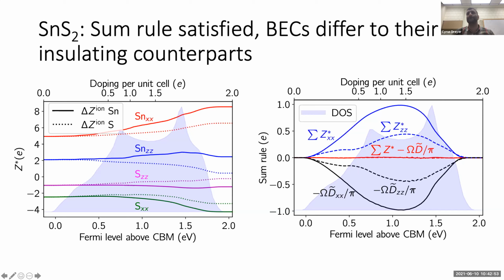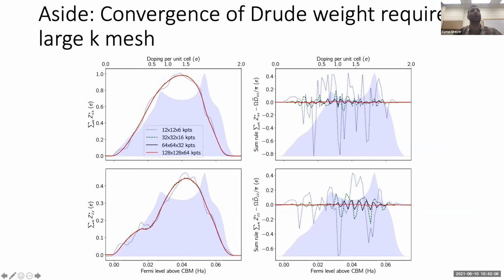And so you might be able to see that there are some little oscillations in the Drude weight and in the sum rule. Just as a technical note, I'll point out that the convergence of these quantities, especially the Drude weight, is quite difficult. We need to go up to very large k meshes, which we do via Wannier interpolation.